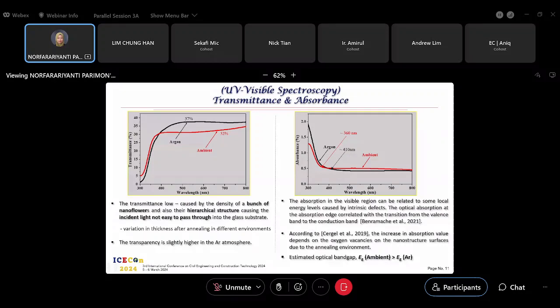So maybe the variation in the thickness of the nanoflower causes the transmittance difference. But for both samples, the transparency is lower than 50%. For the absorbance, we can see for the argon sample, the absorbance edge is below 410 nanometer, but for the ambient atmosphere, it's lower than 360 nanometer. And then we can estimate the optical band gap: the ambient annealed sample is larger than the band gap of the argon annealed sample.